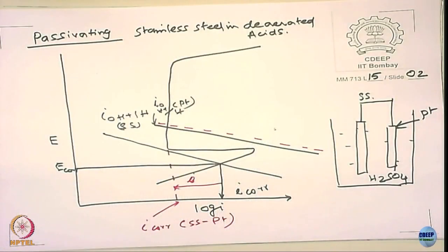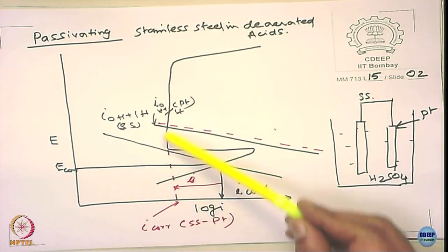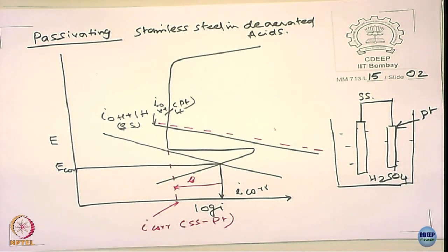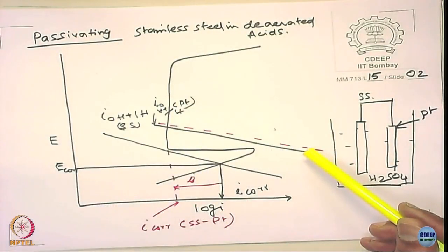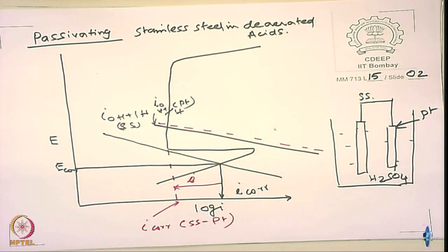Let's go to the situation here. Now, it has moved from here to this. Does it reflect something we discussed earlier? Is it cathodic protection? Is the potential moving cathodic? It is moving anodic, right? The potential is moving anodic. So, it is similar to anodic protection. In anodic protection, you are applying an external current by a potentiostat. Here, you just use a platinum. The platinum can enable the passivation of the metals. I am not saying do it, but it is possible that you can do.